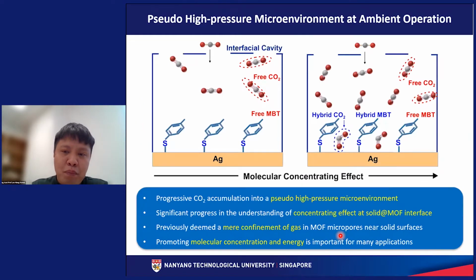So after which we also compare the other SERS spectra or SERS features, and collectively we are able to infer that a pseudo high pressure microenvironment can be created in our interfacial cavity at ambient operation. Okay, so in other words, initially there is nothing inside this interfacial cavity. As we flow more carbon dioxide into our system, CO2 can be captured by the MOF and they will accumulate in the interfacial cavity over here.